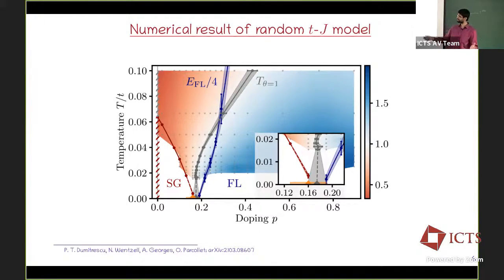And this is related to this thing that we find, that you really can have a situation where the electron Green's function is just Fermi-Liquid like, but if you don't look at some other observables, you would wrongly conclude that it's a Fermi-Liquid. So that's not the complete story. And it's true that if people have done transport experiments in precisely those regions, you do find anomalous behavior, although the photoemission just tells you it's Fermi-Liquid.